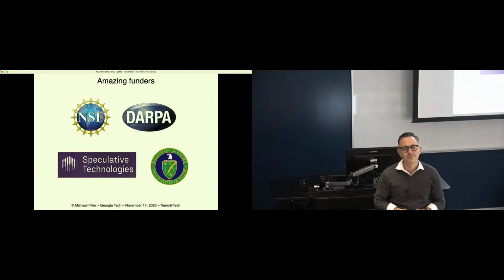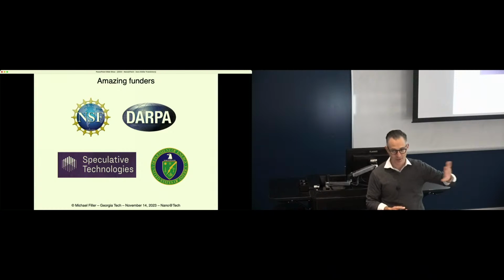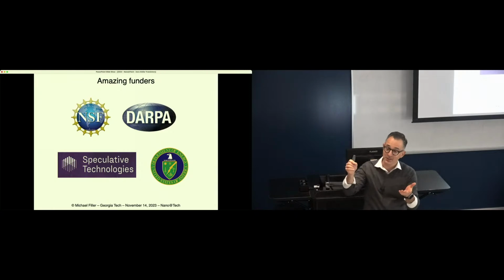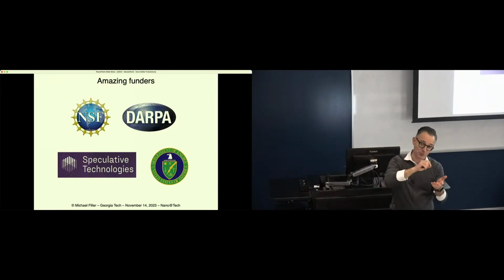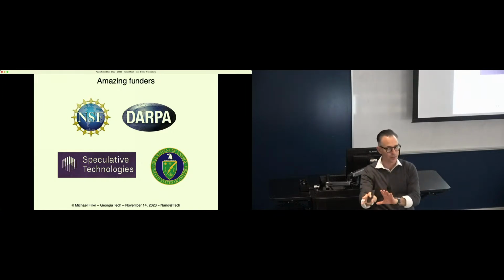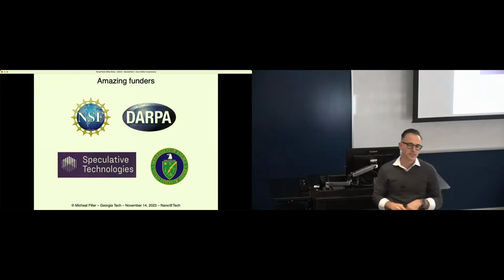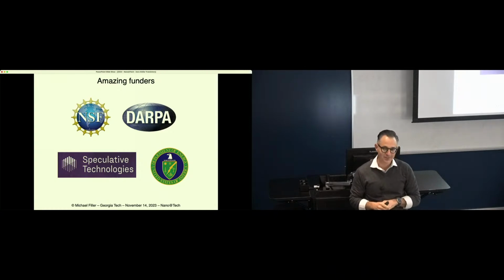And I guess, so what is the harvesting process? Right. So a couple things on that front. First thing is that there's applications outside of microelectronics where you don't need to harvest. So it turns out those crystals inside colloidal capsules are really interesting as processable optical materials. Right, so now that they're in these colloidal capsules and you can flow process them and engineer the optical response through the cutouts in the nanowires or the materials you choose or the core shell structures you might make on the inside, you don't need to harvest. On the microelectronic side, it's a really interesting question. How you do that well, how you stabilize the surfaces of the wires so they don't agglomerate.